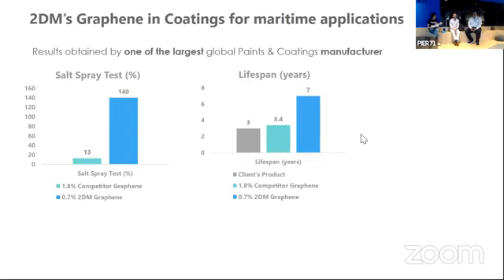At the moment. What they did, they added our graphene to their standard anti-corrosive coating that they use to paint the hull of the ship. They use a three-layer structure for the coating, and they add graphene only to one layer, the active layer, the one that contains zinc. Right. What they could see is that when they added graphene from the competitors, from the market, they got a 13% increase in the performance in the salt spray test. That relates to the lifespan of the coating when it's applied, right?